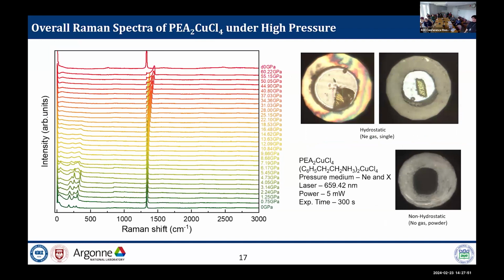Next, this is the Raman spectra of PEA2CuCl4 under high pressure. We measured hydrostatic and non-hydrostatic conditions, using neon gas as the pressure medium. In the sample, we can't see any peak over 400 inverse centimeters.